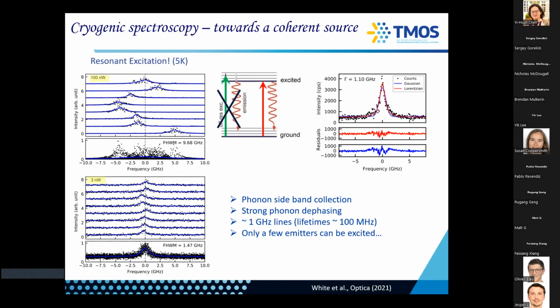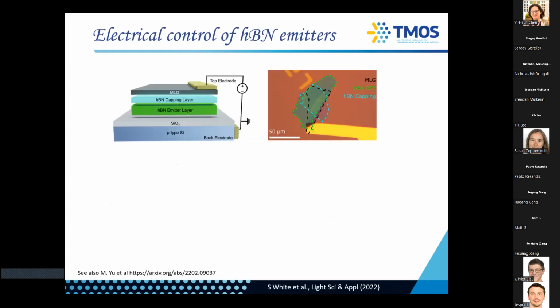How do you avoid it? Well, intuitively, one would think if this all depends on fluctuating fields, you can apply a field and stabilize the emission. And with 2D materials, applying a field is easy. You just make a device. And so we did. So this is our hBN emitter layer, and we cap it with another layer of hBN, and we put graphene on top. The graphene on top is just to provide the contact. So that's our kind of top gate or top contact. And that's all on silicon.